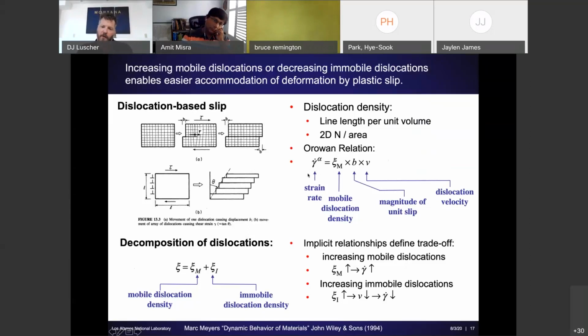Well, that's expressed by the Orowan relation, which says that the shearing strain rate is related to the density, which is a line length per unit volume of mobile dislocations, multiplied by the magnitude of unit slip, which is the Burgers vector magnitude. So drawn here on this figure, again borrowed from Marc Meyers' book, the Burgers vector magnitude b. And the product of those terms with the dislocation velocity. So if we increase mobile dislocation density while holding the other variables fixed, then that means we increase the strain rate at a given dislocation velocity. What that means is if we add more mobile dislocations, we can accommodate more plastic deformation in a finite period of time.